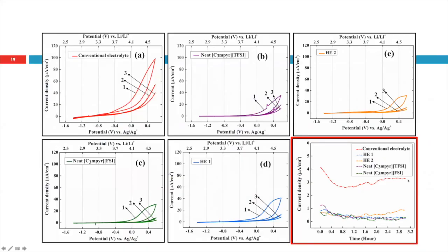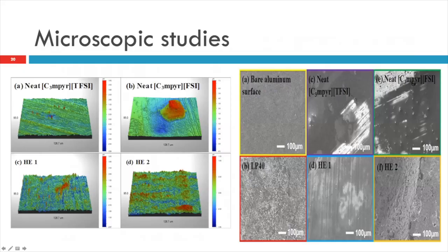One thing we were also interested to know here is, if I use or modify any electrolyte, what type of corrosion behavior you'll see in the anode, in the cathode side, in the current collector. So these were studied, and we see that our hybrid electrolyte is precipitating very nicely, even in the first cycle itself, and then protecting further. That's a good thing if you're using a hybrid electrolyte compared to the conventional electrolyte, and that passivates and actually saves your battery. So this is one of the propositions we have worked on, and we have gone through several experimentations.